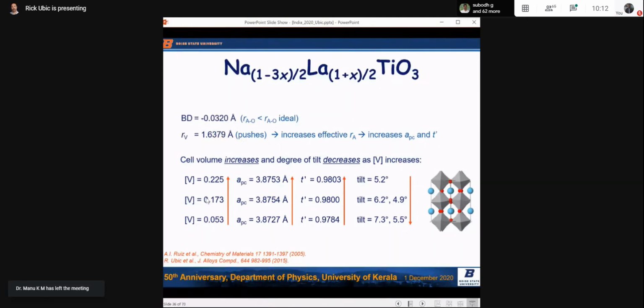The interesting thing here is that we saw as the vacancy concentration increased, the lattice constant also increased, which seems counterintuitive to start with. Vacancies are increasing, but the lattice constant is also increasing. It's because of this. Right? Tolerance factor, T prime, was also increasing, which meant the degree of tilt was decreasing this way. And it all made sense. The model made it all make sense wonderfully.